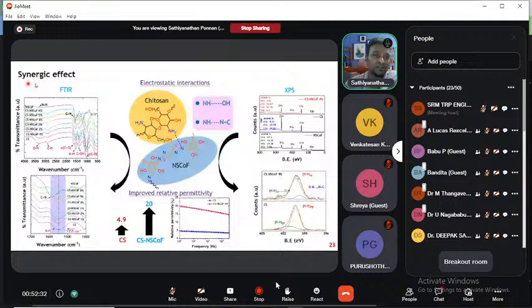And the synergic effect, the first one is surface. So what is the proof for the electrostatic interaction? What is the proof for the improved relative permittivity? We studied through FTIR and XPS, and we observed that among the different weight percentage composite systems, only in the case of 4 weight percent did we observe a significant shift in the 1558 inverse centimeter band. This FTIR band shifted towards a higher wavelength, and this shift was observed only in the 4 weight percent sample. That's why the 4 weight percent showed better performance than the other samples. So why does this shift take place? This shift is due to electrostatic interaction or hydrogen bonding between the NSCoF and the chitosan system.